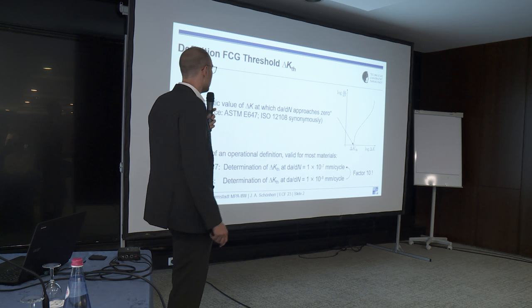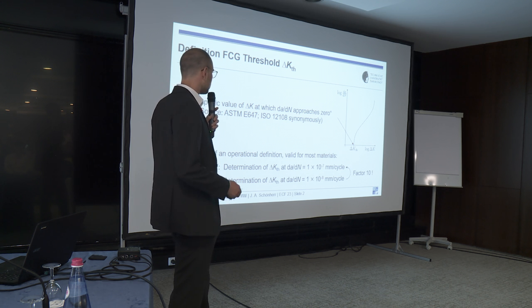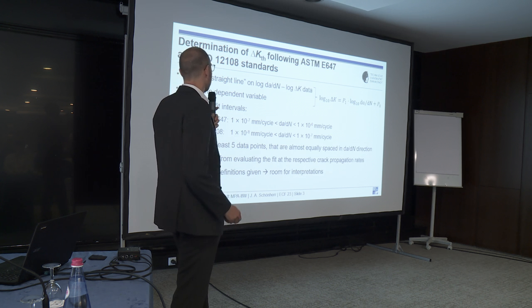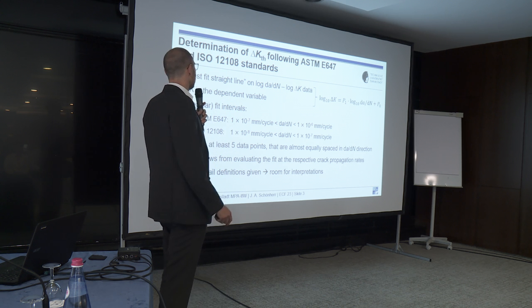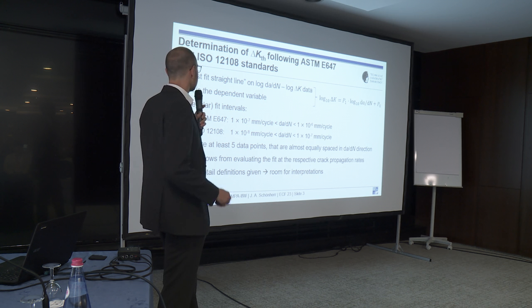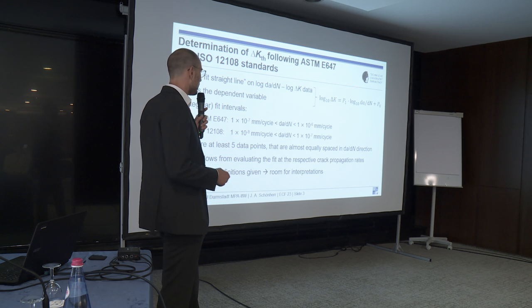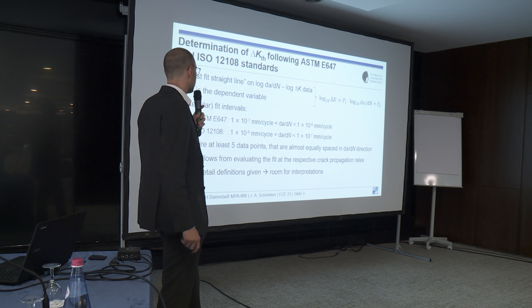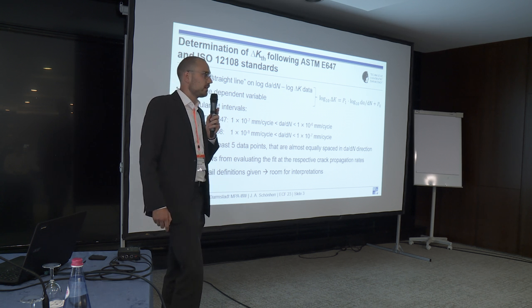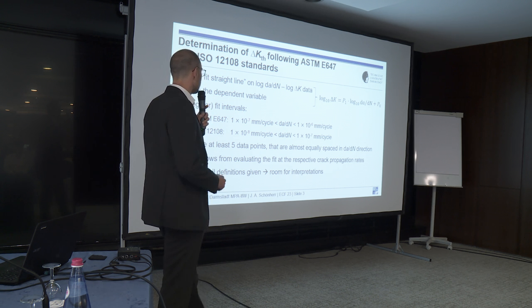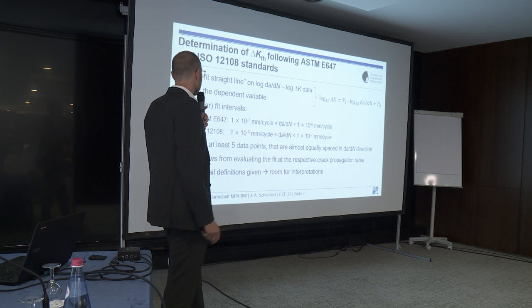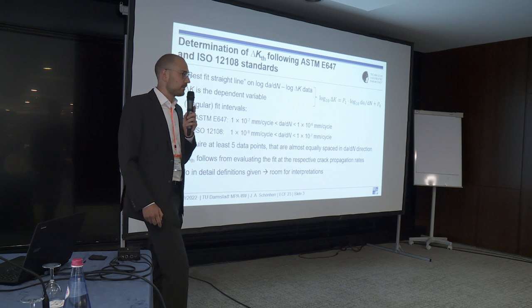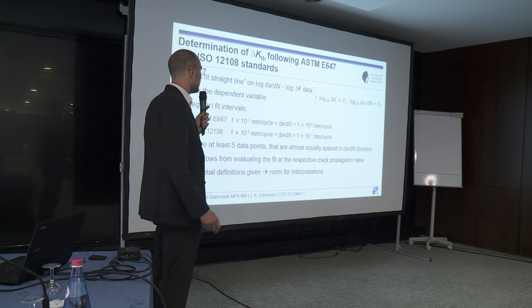When evaluating the threshold against fatigue crack growth from test data, you must use a special fitting suggested in the standard. Both standards suggest using the best-fit straight line to adapt the test data, with ΔK as the dependent variable — a standard linear fit with two parameters in log-log space. The fit interval starts from the threshold crack growth rate and uses one decade of data in terms of crack growth rate.